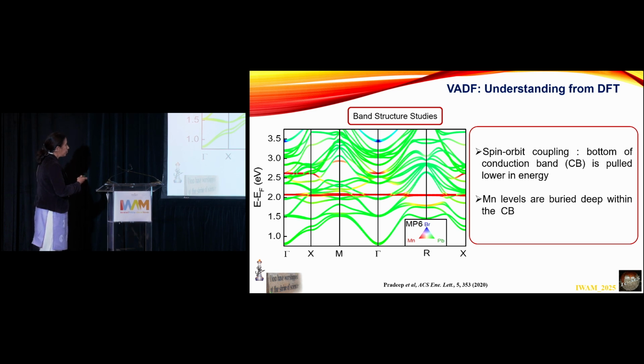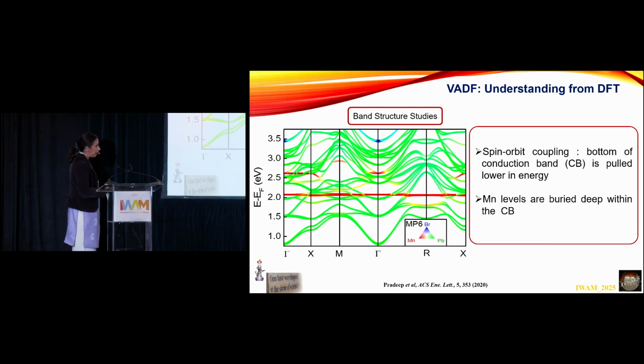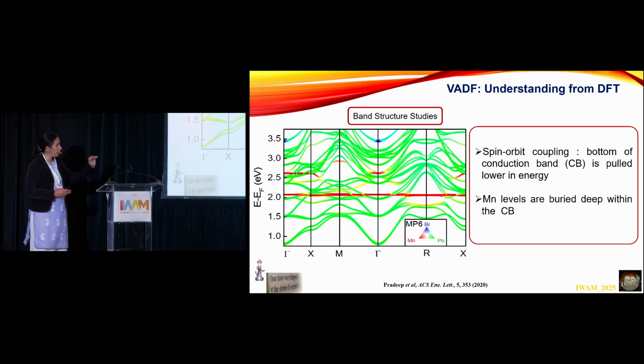The red line here is the manganese. The green line is the host, and you can see that I have used this color code. The manganese is red, bromine is blue, and green is lead dominant states. So anything in between, like orange, is basically a mixture of these two states. So you see here that normally what happens is the manganese levels are at the bottom of the conduction